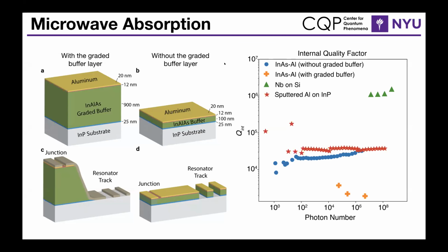And then finally, we were able to measure resonators on our new materials, the ones without the graded buffer layer. And doing them in this style, we're actually able to see resonator quality factors on the same order as those of just sputtered aluminum on bare indium phosphide. These are the red stars.